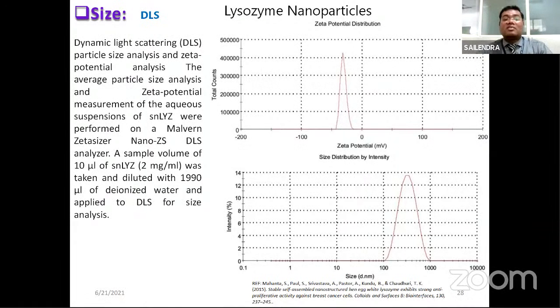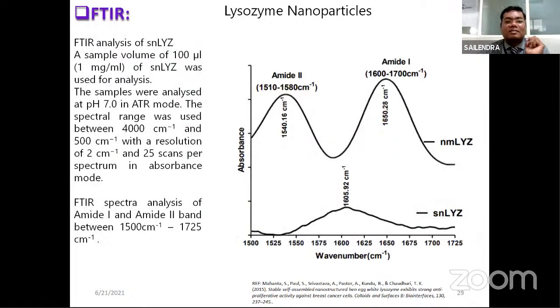if the surface of the nanoparticle is hydrophilic, be careful. And the solvent you are taking for DLS analysis, be careful. If you have a hydrophilic surface, the hydrophilic surface is going to add water molecules and the nanoparticle is going to swell. So in those cases, you will get a bigger size of nanoparticle in the water medium. So you have to replicate the physiological concentrations of all the proteins in your plasma, prepare a similar looking solution, and then you can go for a DLS particle size analysis.